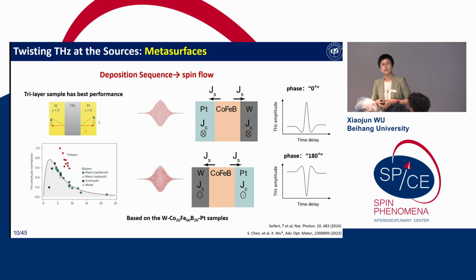Recently, what we demonstrated as a more elegant one is that we directly coat these metals and fabricate the metasurface on this one. This is from Tom's paper, which has already demonstrated that this tungsten, cobalt-iron-boron, platinum tri-layer can give us very highly efficient terahertz radiation. So we directly choose these heterostructures with the optimal thickness.